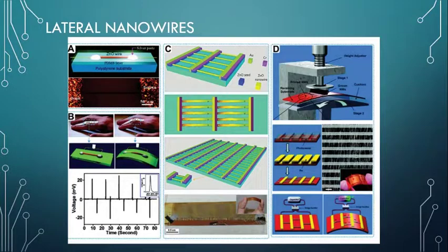A uniaxial tensile strain was induced by the bending of the substrate, which causes a piezoelectric potential along the zinc oxide nanowire, which drove the electrons to flow through the external circuit. A pulse current signal was generated by the zinc oxide nanowire-based PENG in a repeated bending and releasing process, as seen in Figure A. However, the output performance of the PENG based on a single zinc oxide nanowire was relatively low. The open circuit voltage, or VOC, was about 20 to 50 millivolts, and the short circuit current was about 400 to 750 picoamperes, which limited their applications for energy harvesting, as seen in Figure B.